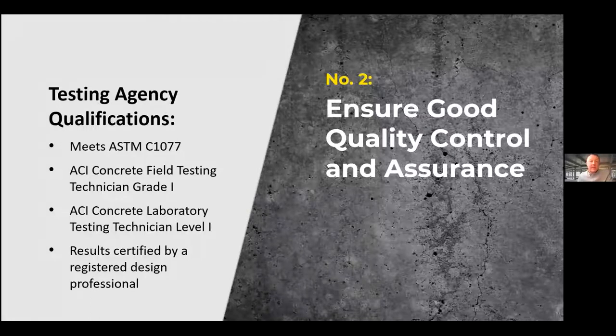Minor variations in sample sets can have reverberating effects on the qualifying performance. We've all seen low breaks cast doubt on performance, only to find cored samples proving performance in excess of design requirements. So there are well-established procedures for taking samples of concrete and preparing test specimens, storing them on site, transporting them to a laboratory, and ultimately testing them to their appropriate ASTM standards. Concrete itself rarely tests well when testing protocols are not followed. If you have cylinders freeze outside or not cured appropriately, you're going to get variations in your results.